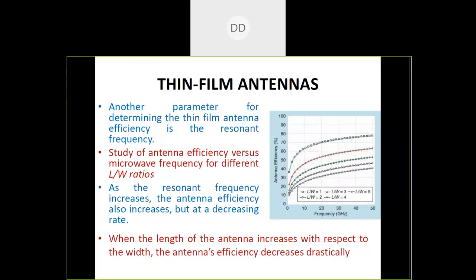Another parameter for determining the film antenna efficiency is the resonant frequency, that is, at what frequency we are using this particular antenna. For a given material conductivity, lower skin depths can be achieved by increasing the frequency of operation. So if we want to use the antenna at a higher frequency of operation, then we can achieve lower skin depths. And skin depth is very important because when we want to design these transparent antennas, the film thickness should be some multiple of the skin depth. If skin depth is more, then that will require a thicker film for the antenna, and the thickness of the film will further affect the transparency of the antenna. But if we are designing the antenna at high frequencies, that results in lower skin depth. This figure shows a plot of antenna efficiency versus microwave frequency for the range between 1 to 50 gigahertz. We can see that as the resonant frequency increases, the antenna efficiency also increases.